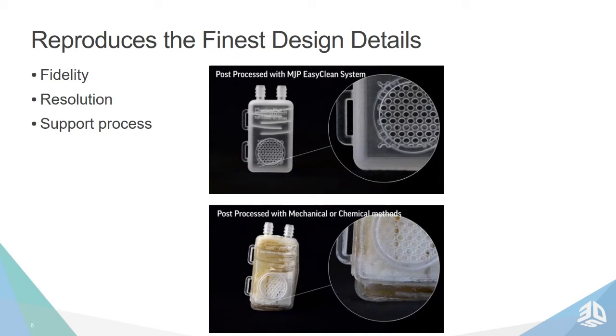And you can see I've put a comparison here. This is MJP, a part with internal geometries and fine holes at the top. And you can see there's been no damage to that fine meshwork of holes. The part remains dimensionally stable and correct, whereas when you're using different support technologies that are not so easy to remove, you either have to blast them away with a water jet, and that would break some of the fine details in the structure itself, or you'd have to use a chemical, sodium hydroxide, which can end up deforming the part, as what's happened in this lower diagram here.